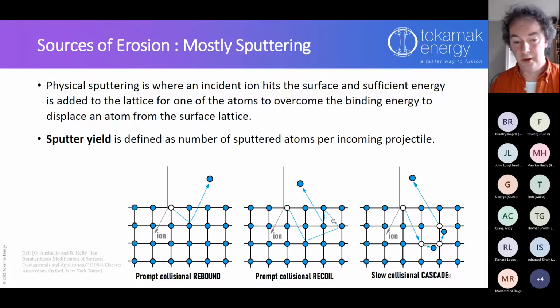But the basic upshot of it is an ion's going in, and if it's got enough energy, or it happens to hit at the right angle and give enough energy to one atom, you're going to lose atoms from the top surface. And of course, once you've lost enough from your top layer, that's one layer of atoms gone, and then another and another and another will erode the surface. And we have a number which is the sputter yield. This is the number of sputtered atoms coming off your surface for each incident ion. So if the sputter yield equals 1, that means that for every ion hitting this surface, you're going to lose an atom from the surface.